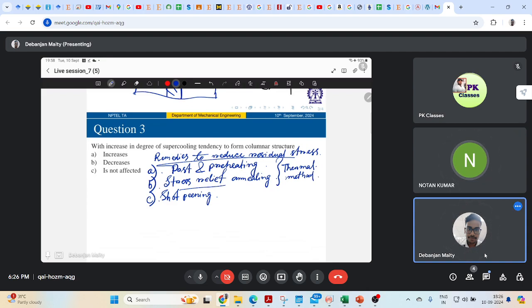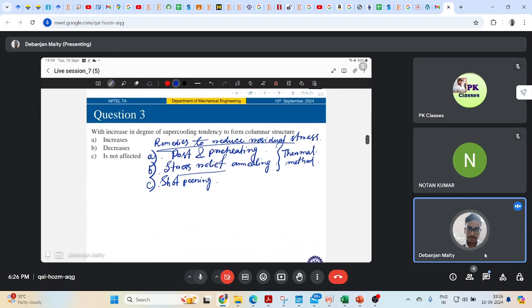What is shot peening? Shot peening is basically you bombard your material surface with small spherical media. There will be some steel balls, through which you provide impact on your metal surface that will generate compressive residual stress. So if some tensile residual stress is there, that will get suppressed. If any crack tendency is there, that will get suppressed because of shot peening. Then you can have some surface rolling. Basically you have to deform the metal.